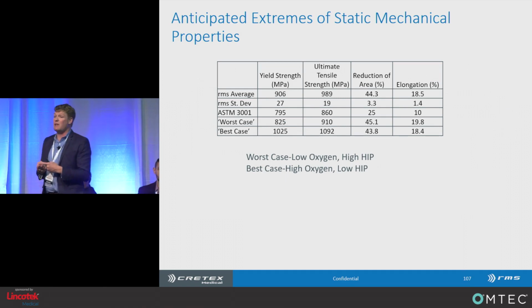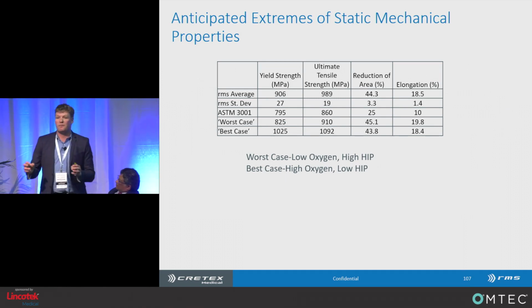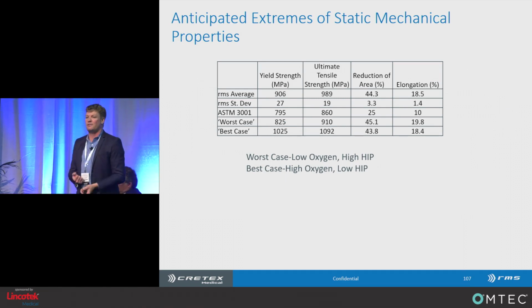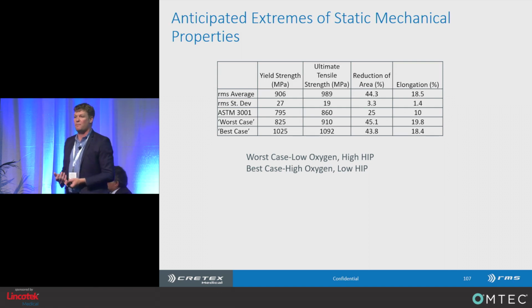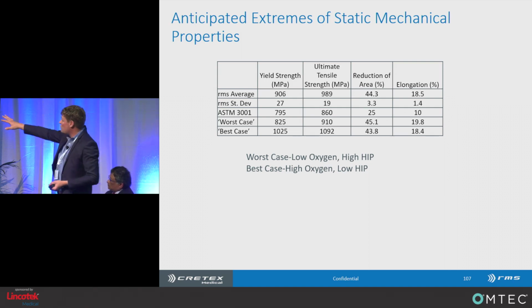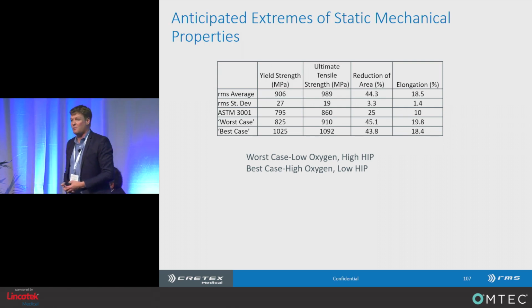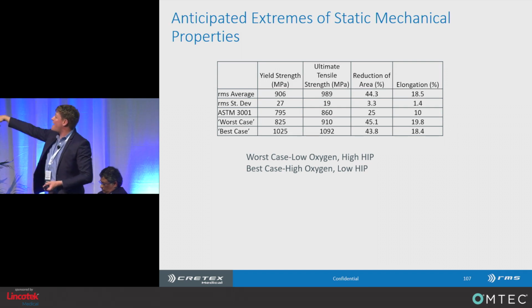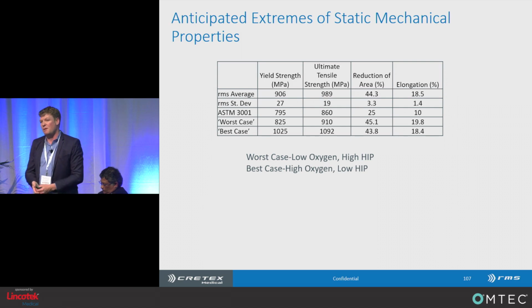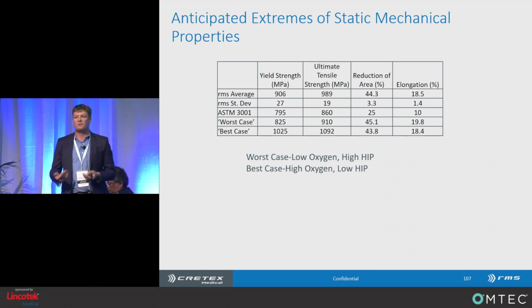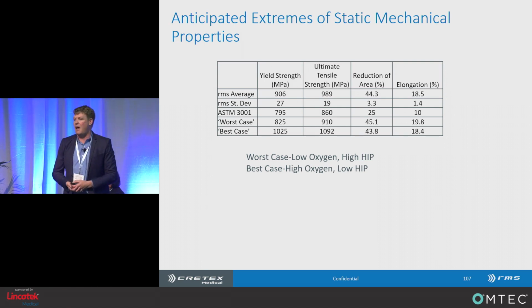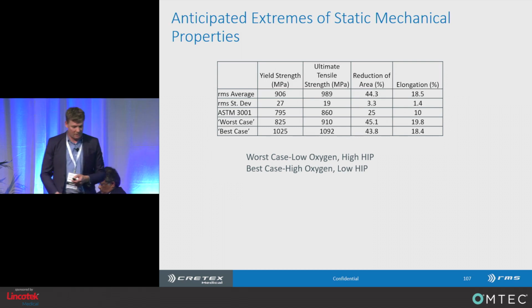So you combine hipping and oxygen content and ask yourself, like, how can I influence the static mechanical properties of Ti-6-4? You can kind of see here, I did some calculations on what the worst case and best case for yield and tensile strength would be out of our material. And you can see you can get like nearly a 20% difference in mechanical performance just by altering the heat treatment and chemical composition of the material you're taking.